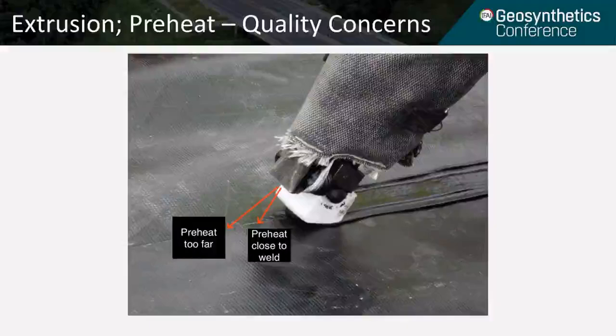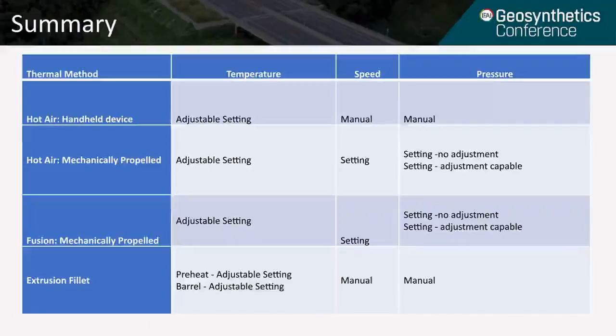And one of the concerns here illustrated is the angle at which the preheat is aimed. If it's too far of an angle, your preheat's not going to be as hot and it's not going to warm the geomembrane up properly. And that really is especially true in cold weather. This slide shows a summary of the different welding methods we discussed and how the temperature, speed, and pressure are adjusted for each of those welding methods.